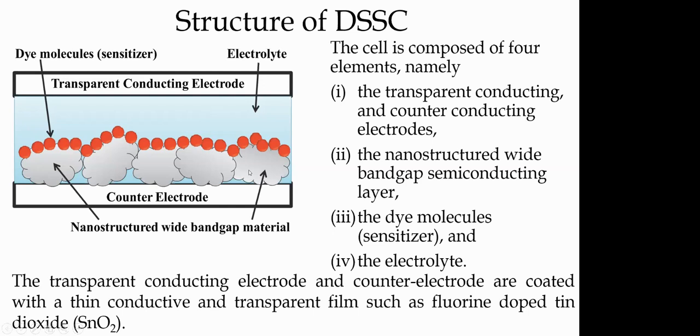In the electrolyte, that's there. So transparent conducting oxide is mostly used as a fluorine doped tin oxide substrate. Then the counter electrode used so far is a platinum coated FTO. And nanostructured platinum catalysts are used to enhance the catalytic activity of transformation of I3 minus to I minus continuously, to compensate the holes in this circuit as well.